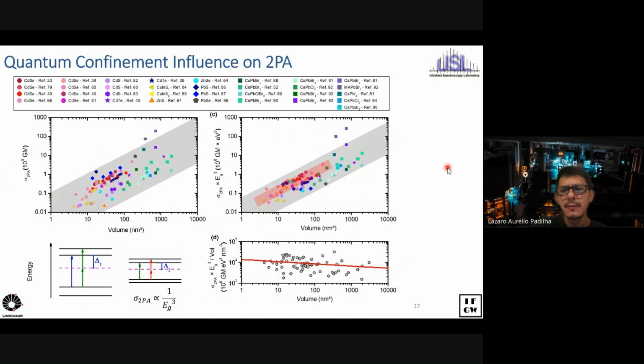So this is somehow frustrating because it shows that it doesn't really matter what you do with a quantum dot. The two-photon absorption cross-section is going to follow just a volume scaling, and there's not much you can do about it. However, if you really pay attention here, there are these blue diamonds and these blue dots here. These blue diamonds, they follow something different. These dark blue and light blue diamonds are for lead sulfide quantum dots. And if you look, the trend here for these is slightly different.